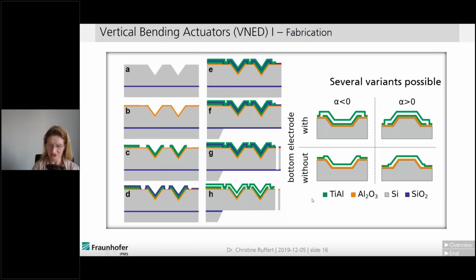Next, the insulation, silica, is deposited in step D. And further on, we have another titanium aluminide layer. And in the next step F, we have a backside etch up to the oxide layer, which defines the cantilever thickness. And the next step, G, we define the rim, the outer shape of the cantilever. And finally, SiO2, so the silica is removed here to void the air gap and also to free the bottom part of the cantilever.